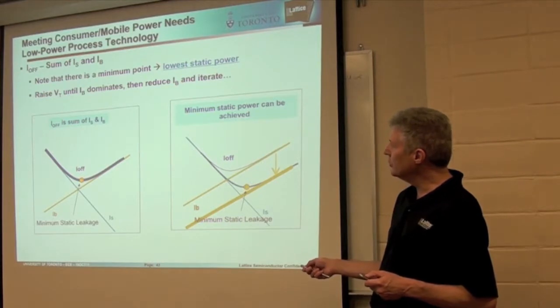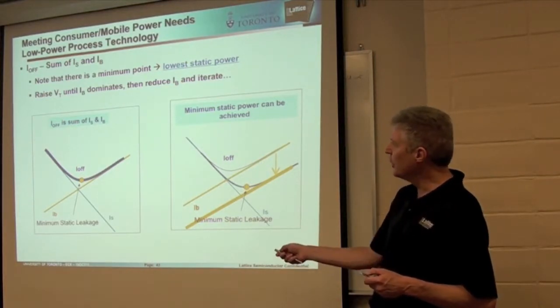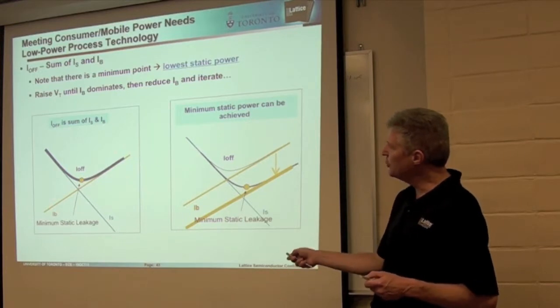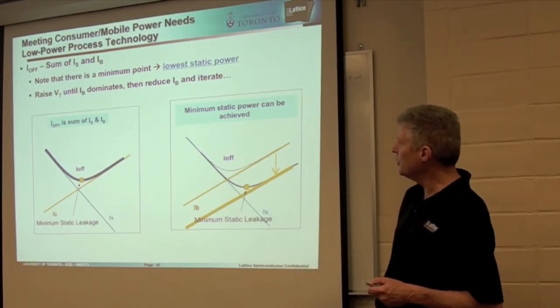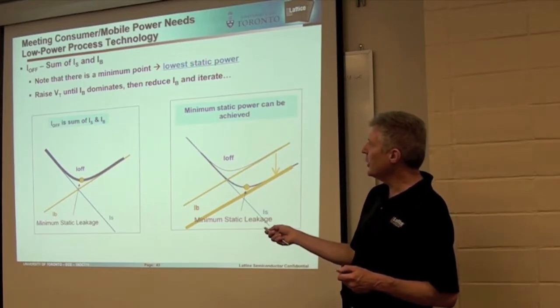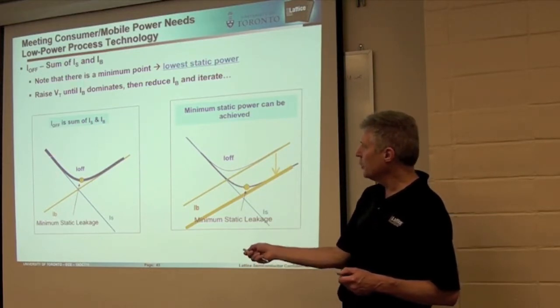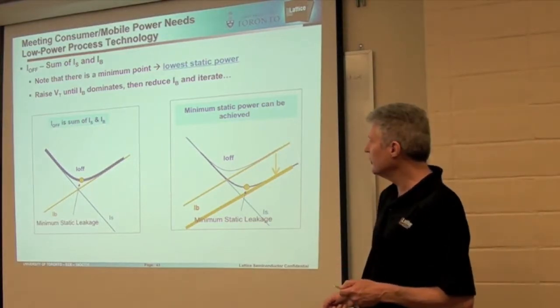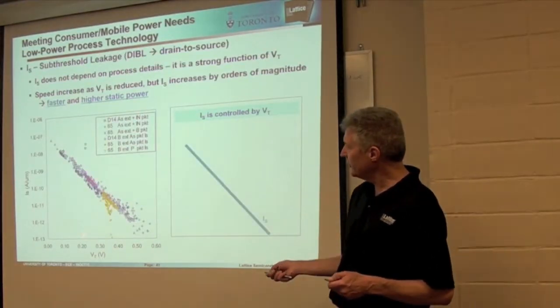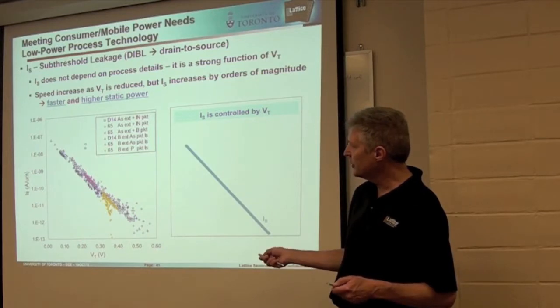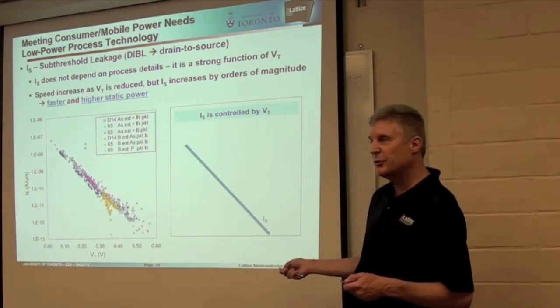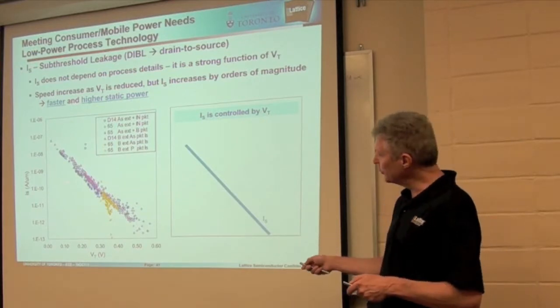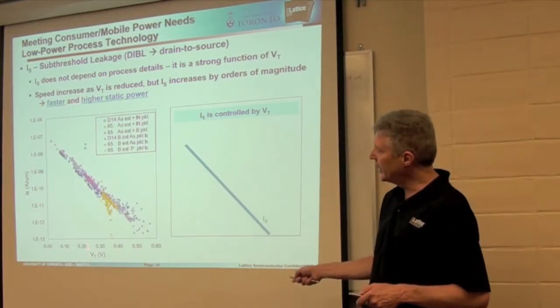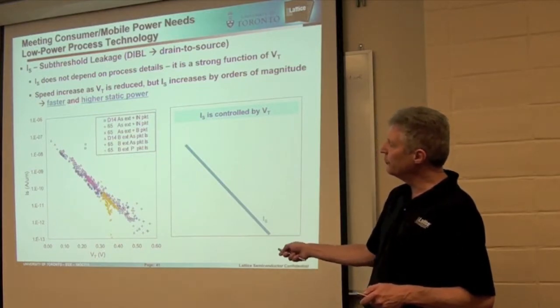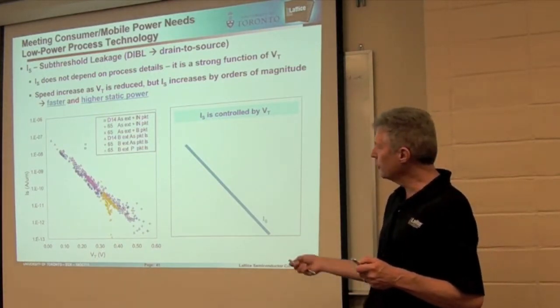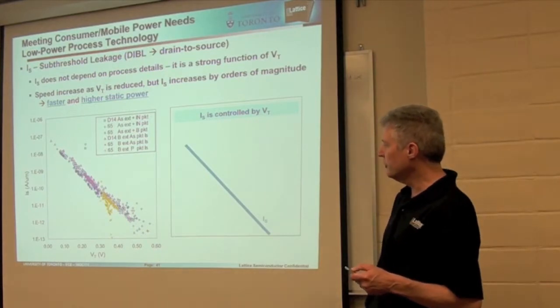So in terms of getting the lowest static leakage on a process, you want to optimize your subthreshold leakage and your drain leakage and get to that lowest point. So the way you do that is to raise your VT, start down here at a low VT, and by the way, today's technologies, let's go back to this one. Today's technologies are running with about 200 millivolts of threshold voltage. They used to be about 500 millivolts, but as we scale the technology and scale supply voltages, everybody's going this way, and so threshold voltage is dropping, and this is what's causing this characteristic to become dominant in terms of leakage power.